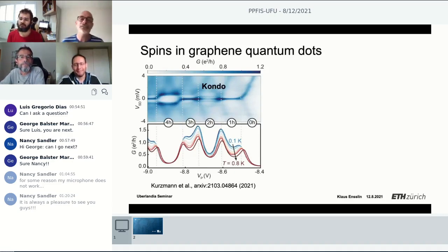So I have to be honest with you that this is the only quantum dot that we investigated in great detail. There are others that show a little bit of Kondo, but it's not so simple to tune it. And you see, the problem is in gallium arsenide, the tunneling barriers can be controlled from nothing to everything because you have a band gap. Here, if you open it too much, you're always limited. You have to keep your Fermi energy in the band gap in the lead. And we cannot completely close it. I mean, I showed you we can go to gigaohms, but in gallium arsenide, you can go to one electron per week. That's not possible here. At the same time, we cannot open it as much as we can in gallium arsenide. We are limited, unfortunately.